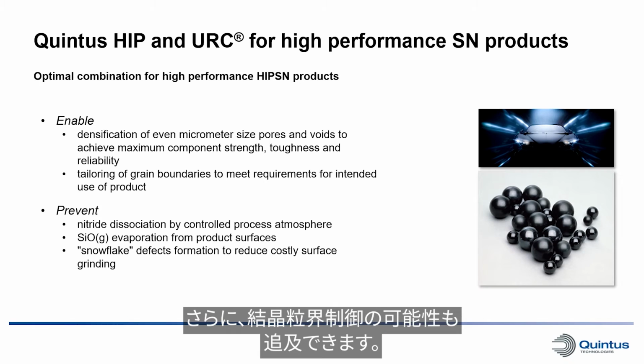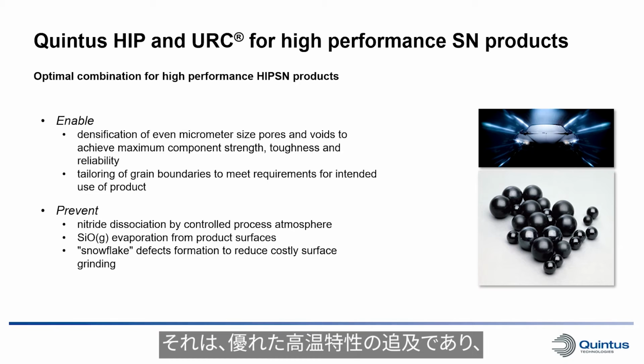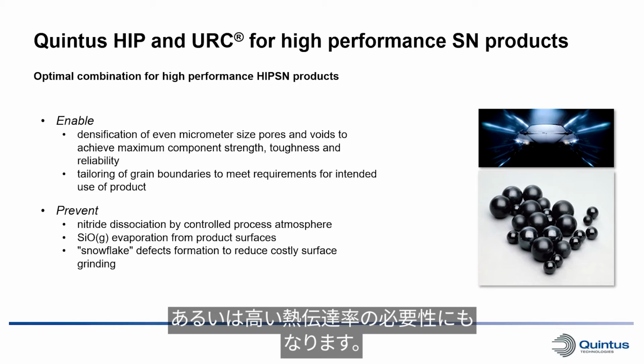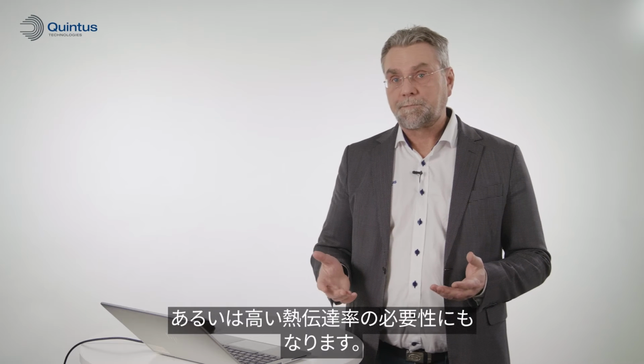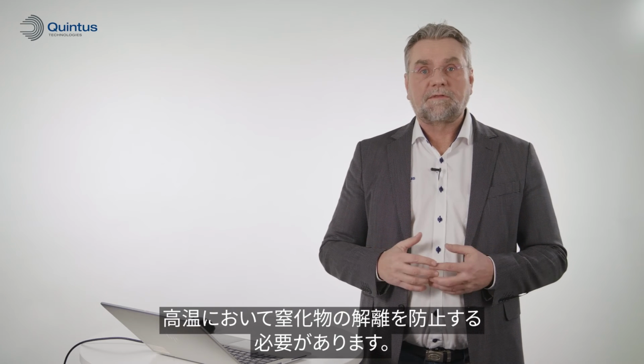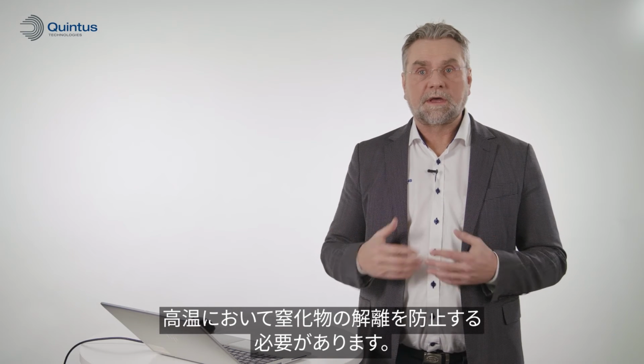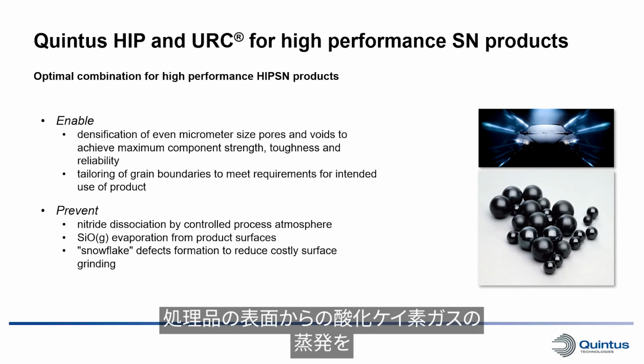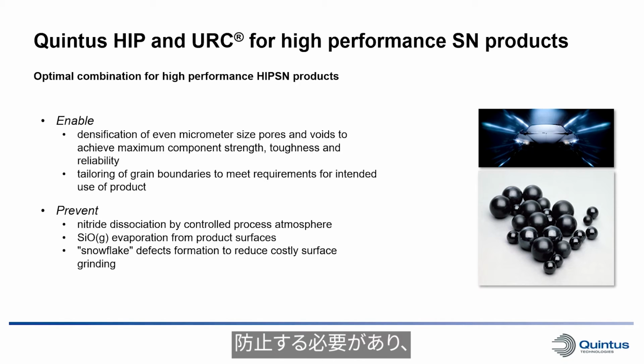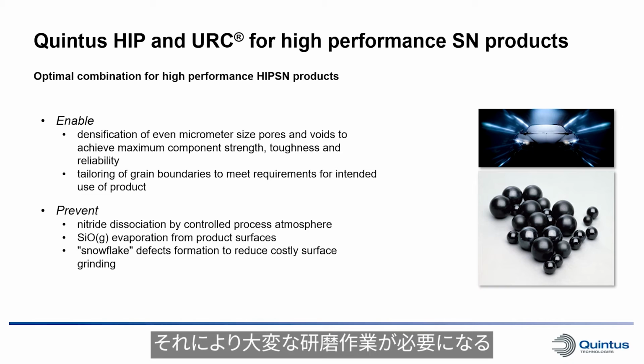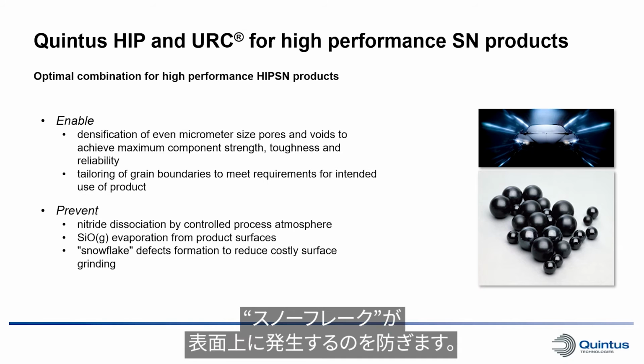We also, if we would like to have the possibility to tailor the grain boundaries, it could be that we want to have good high temperature properties, or that we need high thermal conductivity. Of course, we need to prevent that the nitrides are dissociating at high temperatures. We need to prevent silicon oxide gas evaporating from the component surfaces, so we don't end up with snowflake defects in the surface that will need extensive grinding.